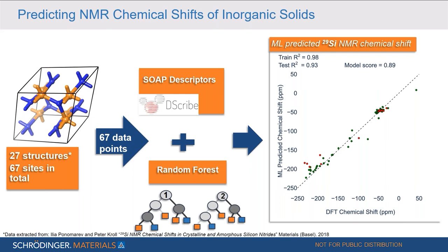And in total, they had 67 unique sites of silicon, so unique chemical environments of silicon. So in total, there are 67 data points. In this example, a random forest algorithm was used. And we see that also for these not so many data points, actually, the results are very good. So both training and test set have an R-square value of above 0.9.